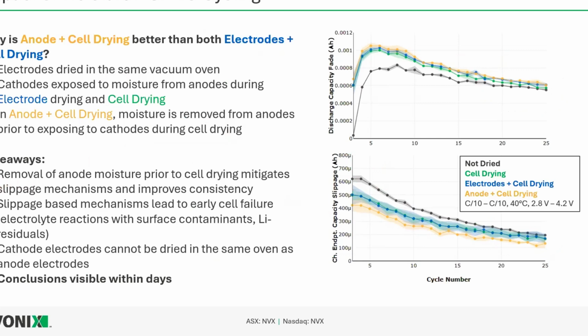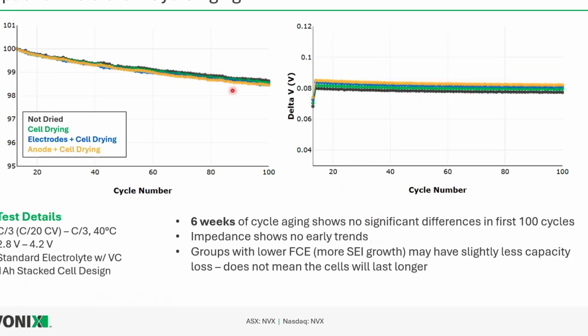So our takeaways from this were that the removal of anode moisture prior to cell drying mitigates these slippage-based mechanisms and improves consistency in our cells off of our prototyping line. And these slippage-based mechanisms, as we've seen before, lead to early cell failure. They lead to things like electrolyte dryout, lithium consumption out of the electrolyte. And these can be due to electrolyte reactions with surface contaminants on the cathode after reacting with moisture, lithium residuals, etc. And then we also have as a conclusion from this that cathode electrodes can't be dried in the same oven as anode electrodes. And we were able to make these conclusions and see these differences just in a couple days, rather than waiting weeks and weeks until we see something appreciable happening here.